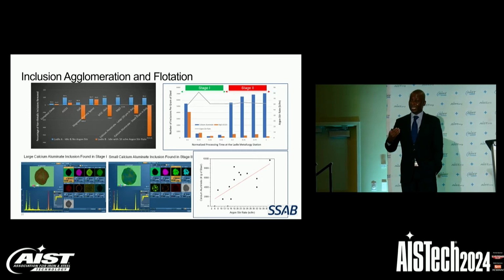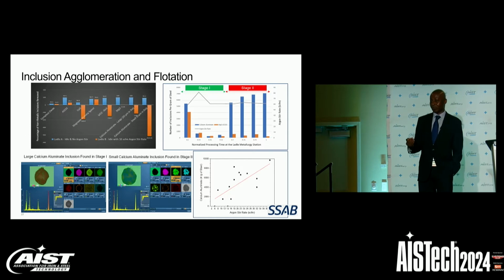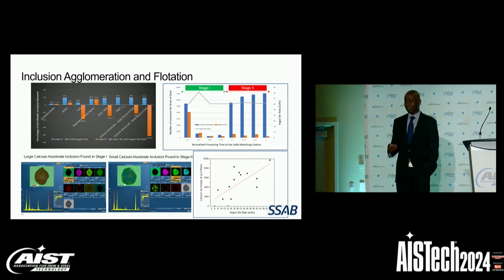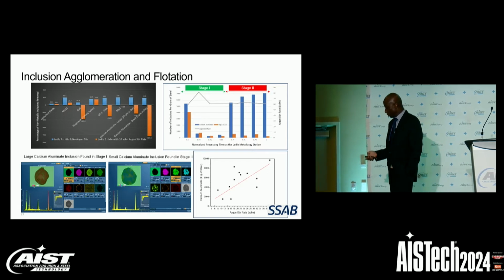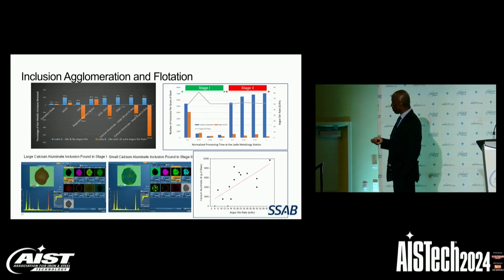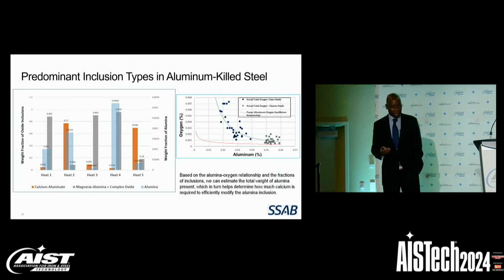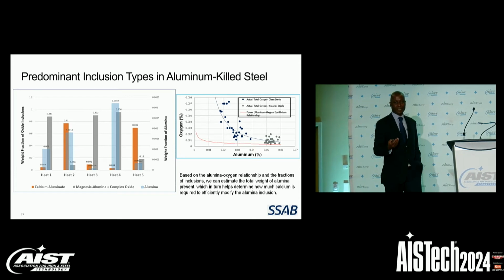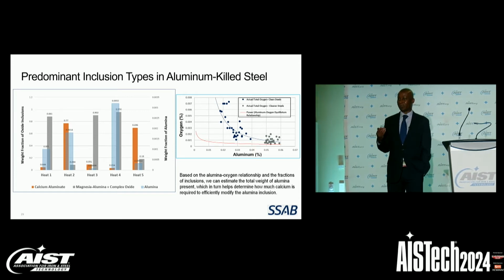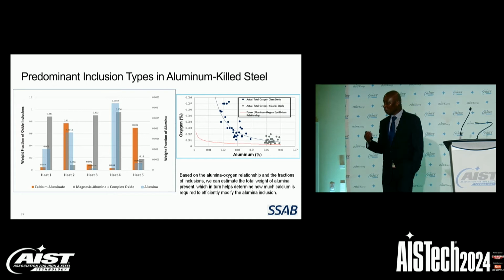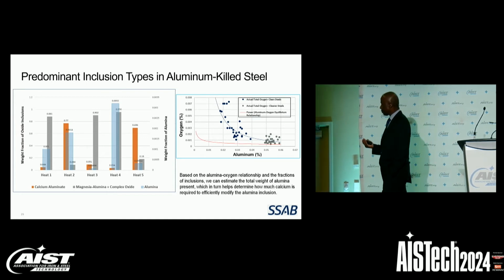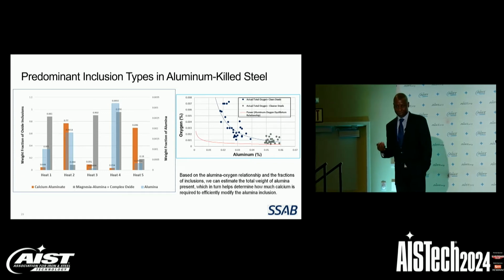And then not only that, because the slag is fluid, if you are stirring aggressively, you entrain slag particles back into the steel. So what we found is that, in stage two, the population density of slag particles that is entrained back into the steel is directly proportional to the argon stirring rate. But overall, we found that, in aluminum-killed steel, pure alumina is not the predominant inclusion in the steel. Most of the alumina is tied up as calcium aluminate, magnesium aluminate, and complex oxide.